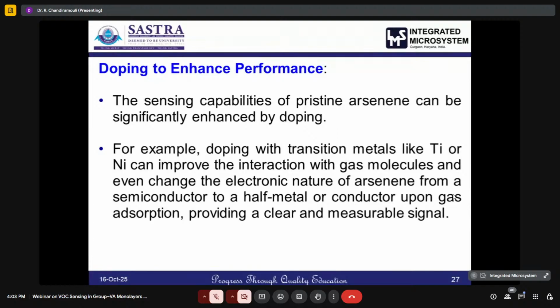We can also make use of doping and functionalization to fine-tune the material, doping to enhance the performance of arsenene. The sensing capability of pristine arsenene can be significantly enhanced by doping. For example, if you dope arsenene with a transition metal like titanium or nickel, it can improve the interaction with gas molecules, and it can even change the electronic nature of arsenene from a semiconductor to a half metal or a conductor upon gas adsorption, and that will also provide a clear and measurable signal.